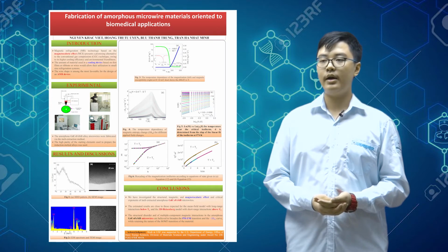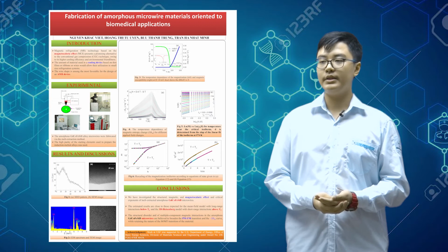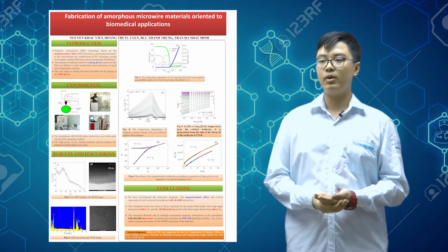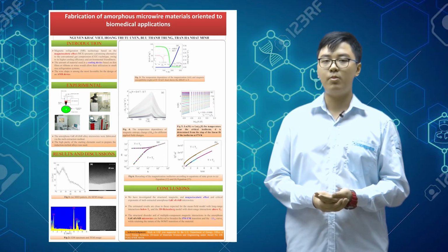Gd is a high saturation magnetization ferromagnet with its Curie temperature at 294 Kelvin and large peak values of both delta SM and delta T ad, making it an excellent magnetocaloric material for sub-room temperature AMR. However, its high cost limits it from practical use.